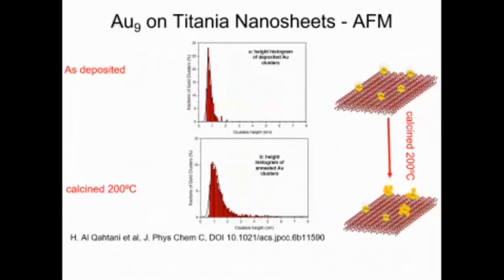The gold 9 on titanium nanosheet, as deposited, we have around 1.2 nanometer. This is with the ligands. And when we annealed this gold nanocluster, we saw it getting higher in height. And this is quite a bit of annealing, and this is the aggregation degree for our gold 9.